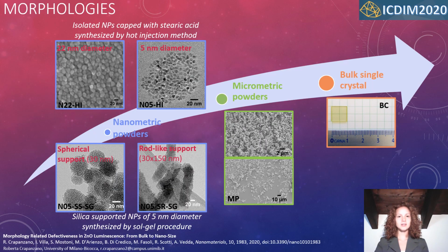The 6 zinc oxide specimens include 4 nanoparticles synthesized by our group, and micrometric powders and a bulk single crystal purchased from outside companies. In particular, regarding the nanometric samples, we studied 2 bare nanoparticles of diameter of 22 and 5 nanometers respectively and grown by hot injection method. Moreover, we studied 2 zinc oxide nanoparticles of 5 nanometer diameter supported onto spherical or rod-like silica nanoparticles and grown by sol gel procedure.